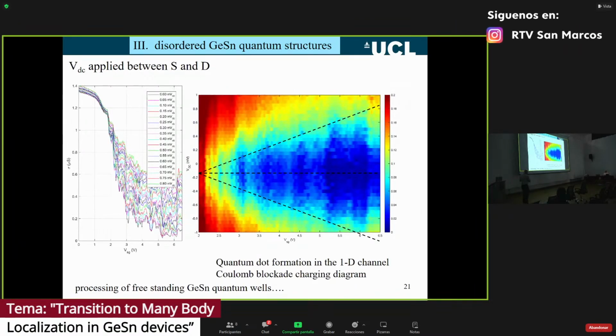We can confirm that by applying a DC voltage, that is, applying a DC voltage along the channel between the source and the drain. If you plot that out as a false color plot, this is device conductance plotted as a function of split gate voltage, and the y-axis is DC voltage from 0 to 1 millivolt and 0 to -1 millivolt. And we see here the Coulomb diamonds. They're not quite quantum dot Coulomb diamonds because the system is very, very well connected to the source and drain regions of the device. But nevertheless, we can see that we have a charging energy of something like 0.4 meV. So the system goes over to a series of random quantum dots.